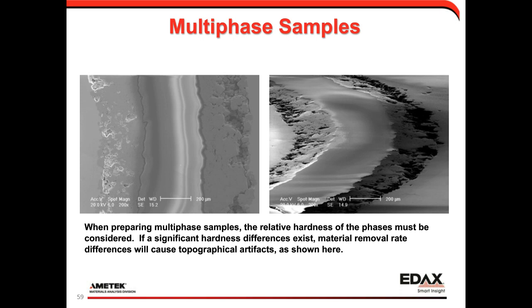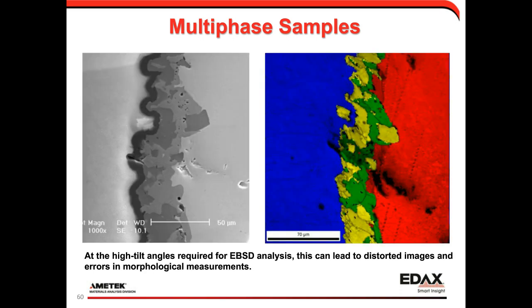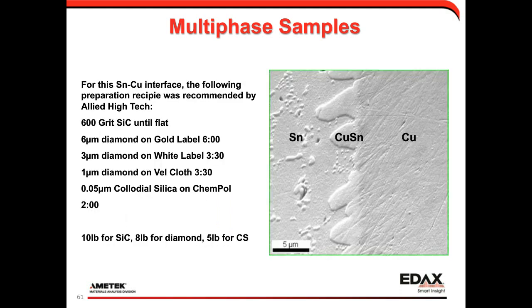And so when we look at a particular grain structure flat, that shows us what the structure looks like. But when we look at this tilted, because the sample is not just tilted to 70 degrees, but there's also a tilt orthogonal to that, our beam is not going exactly where we think it's going, and so it distorts the microstructure. For texture and phase analysis, that's not going to be important. For any morphological grain size, grain shape type measurement, that's going to be a problem. So this is just a nice example of a multi-phase material to try to prepare.